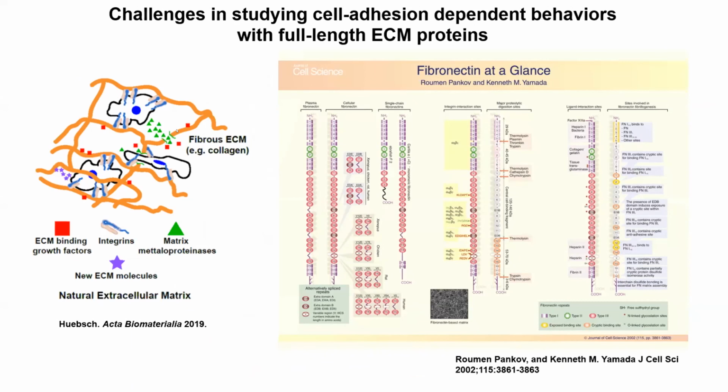There are also peptides that can be degraded by specific enzymes. So if we cross-link our material using these matrix metalloproteinase responsive peptides, that's another way to elicit cell migration. And a third way to elicit cell migration is to make the material not be a purely linear elastic material. If we make the material have some plasticity to it, so that cells mechanically can induce a permanent deformation in the material, then through their traction forces, the cells can basically open up pathways for migration.